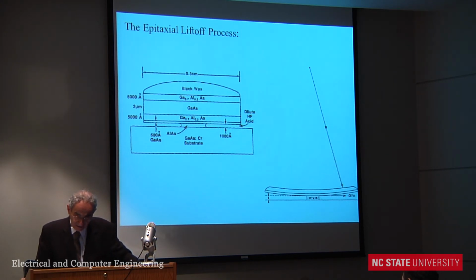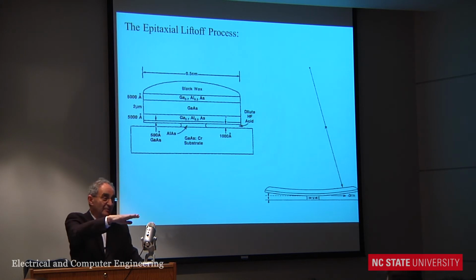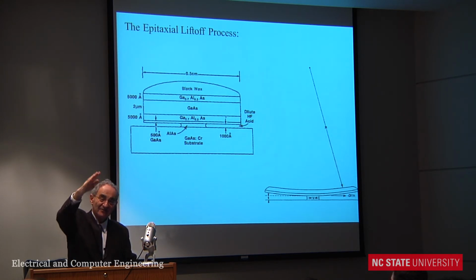And this is a process I developed when I was working under Dave Asmus, and that is to take advantage of something that is kind of amazing, and that is etch selectivity. If you go to the Handbook of Chemistry and Physics and look up the inorganic compounds, now nobody does this because you have the web, but in the old days we actually had the volume. It was a very thick volume. And then you look up the inorganic compounds, and it has a list of all of the known inorganic compounds. And then it tells you the color, and it tells you the melting point.